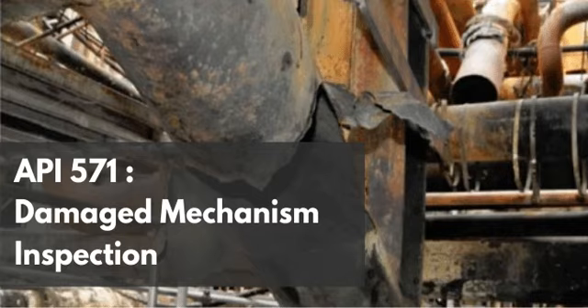Okay, so if you're combing through piping specs, anytime you see 430 or 446, those chromium percentages should immediately trigger a red flag for you. Definitely. But the 400 series isn't the end of the story, is it? Because the code also pulls Duplex stainless steels into this. It does, yeah. And for very good reason. Duplex stainless steels are definitely on the hit list.